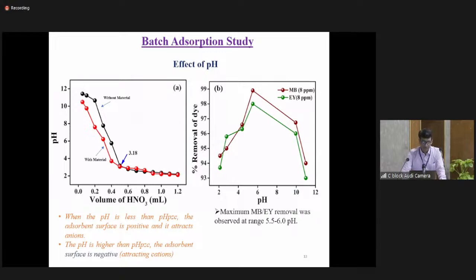Okay, so you see there's a graph A. There are two materials, in which we change the pH value by adding some nitric acid, and a titration study was carried out without the adsorbent and with the adsorbent. Where these two graphs meet, that point is called pH-PZC. That is around 3.18. When the pH is higher than pH-PZC, the adsorbent surface is negative and attracts more of the cations.